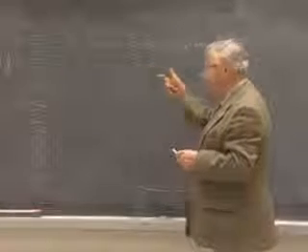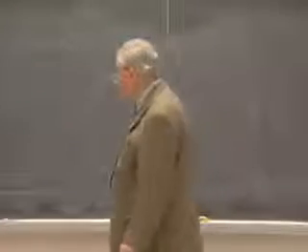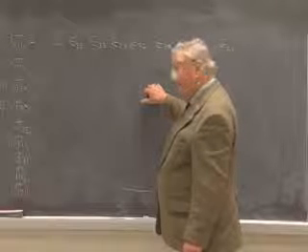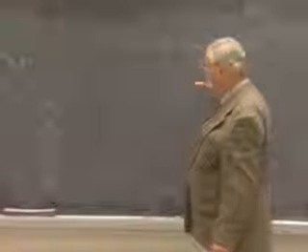9 terms, 9 terms. And in between is going to be a tensor consisting of 9 by 9 elements. There will be 81 different coefficients in here. If we want to derive symmetry constraints, we're going to have to, for every one of those 81 elements, do a transformation. And each transformed element is going to be a sum of 4 direction cosines times 1 tensor element, repeated 81 different times. Not something to be undertaken on a short afternoon.